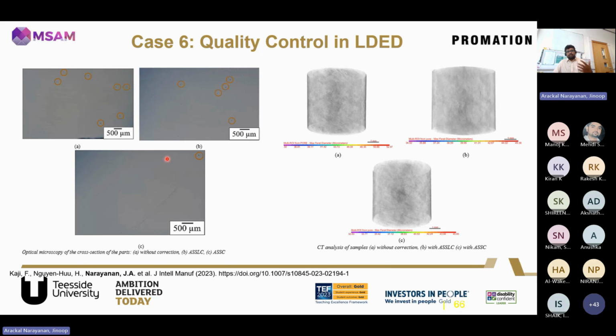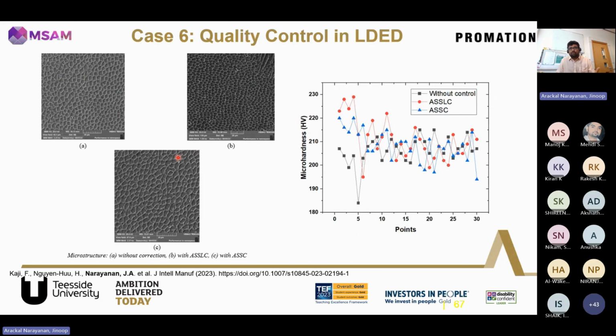As we are controlling the scanning speed and the laser power during manufacturing, it's very important to understand whether this is having any bad effects on the final product. So we did quality control checks, cross-section analysis, and CT analysis, and we could see that there was largely no huge impact on the defects formed. In fact, there were minor defects in the laser control samples, but largely it was defect free. And we could not see any huge variation in the grain structures as well.